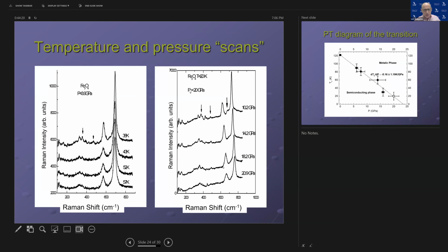And so when you do it, you can do several things. For instance, you can keep pressure constant, and then you can change the temperature. And when you see additional lines popping up, you can immediately say, hey, this is where the transition temperature takes place, because new additional lines mean that the sample is in its less conducting state, because I know that its structure becomes different, its unit cell becomes bigger. What you can also do, you can keep the temperature constant and change pressure, and that allows you, again, to find the transition temperature as you change the pressure. So that allows you to measure different pressures and temperatures and create this phase diagram. And again, the trick is to detect additional lines. If you detect those additional lines, this is where the transition takes place.